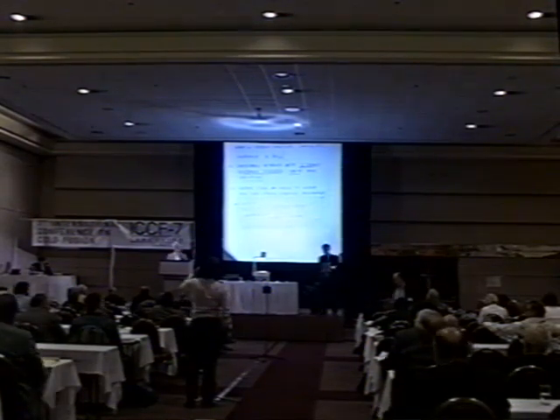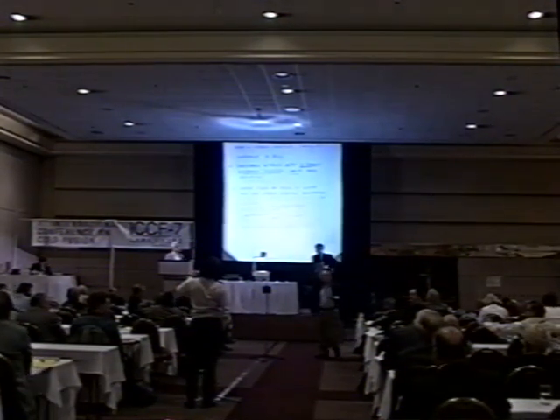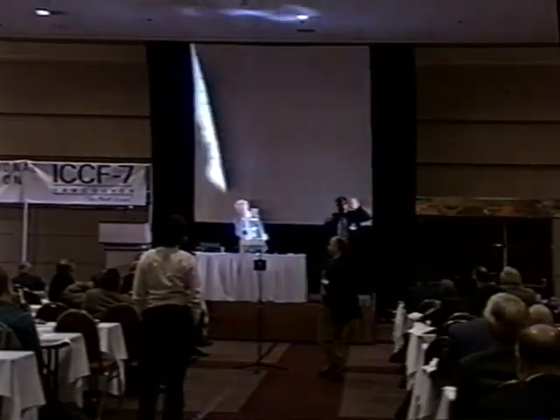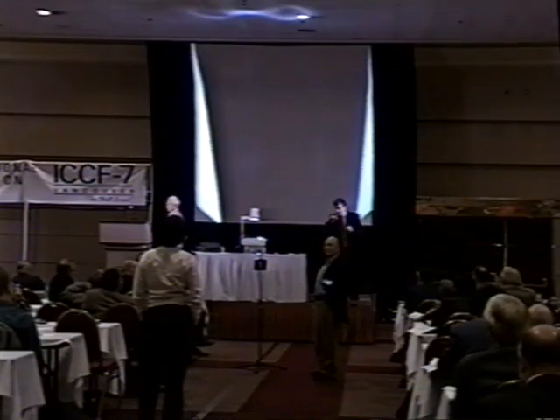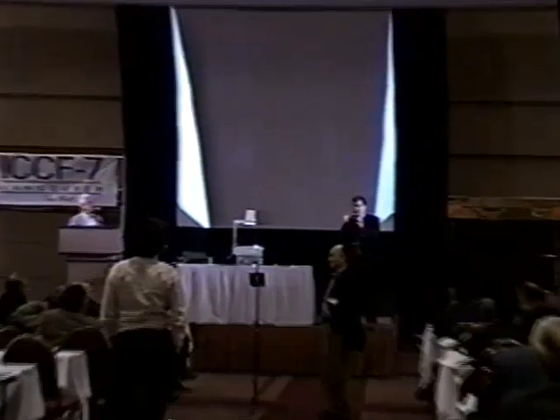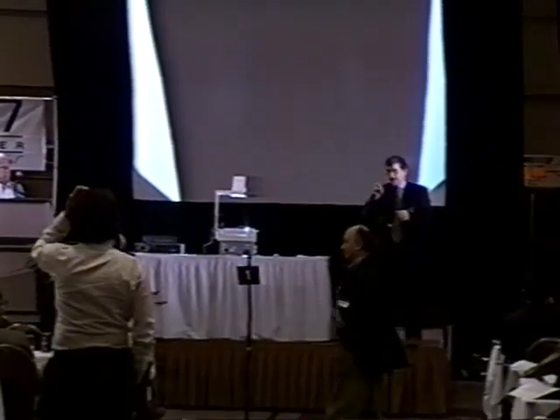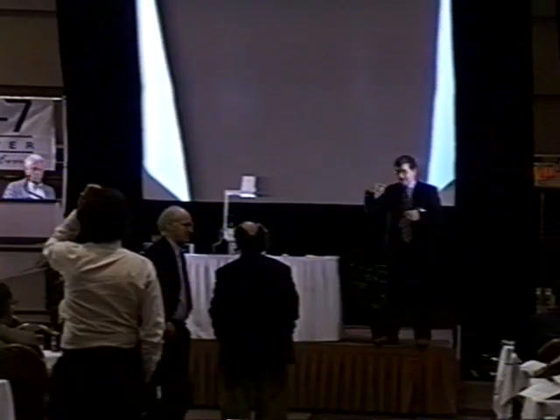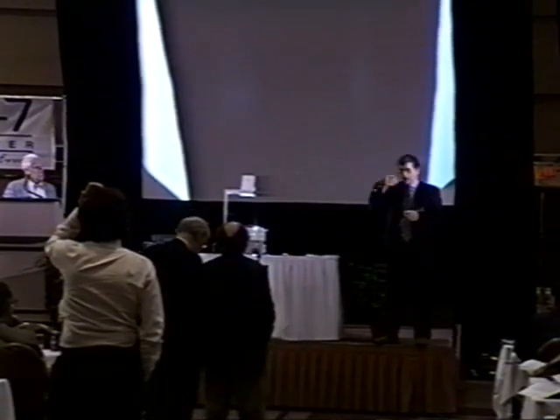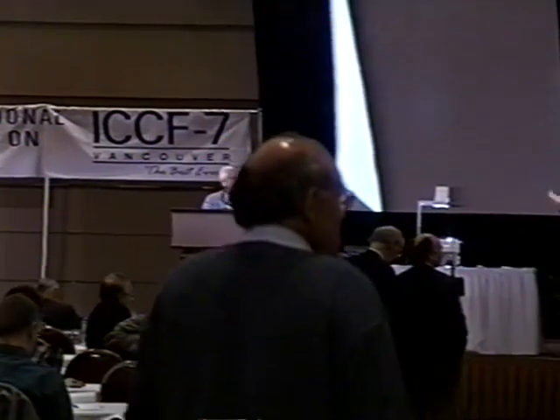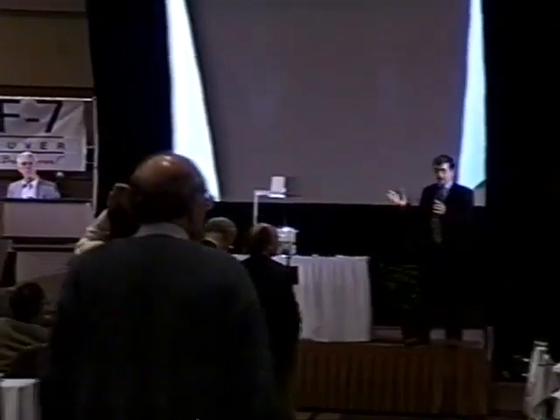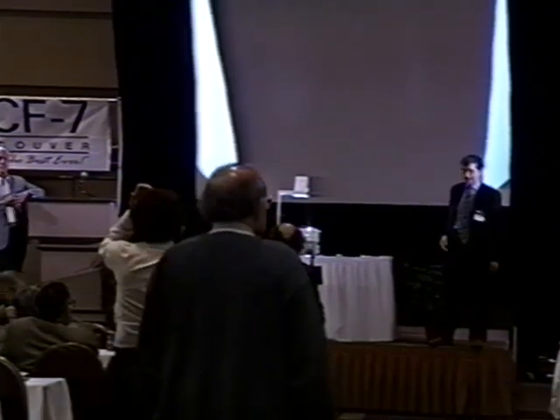Sure, there are questions. Yes, please. Larry Forsley from JWK. A couple questions for you. One, are you sure that you haven't plated out the inside with thorium? Yes, we checked if there is some thorium inside the cell, because we built a special alpha detector that checks very, very narrowly the inside of the cell. Check if some thorium remains. Moreover, we scratched the surface mechanically, dissolved all the cell in hydrochloric acid, and we analyzed all the material collected with alpha spectra and total radiometric.